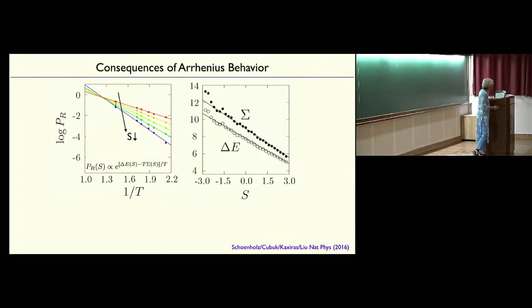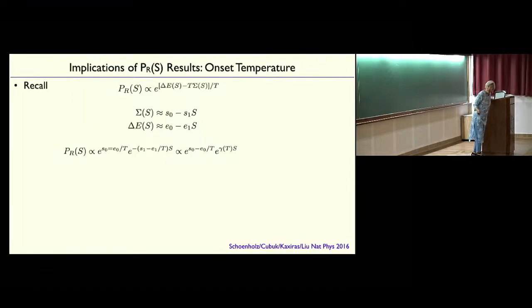All right, so the consequences of this. You see here that the energy barrier is roughly linear and the entropy barrier roughly linear in softness. So it looks something like that. Now let's stick that into this expression. And what do you get? Just stick these dependencies into this expression. You can factor it into two terms. One of them doesn't depend on softness. That's supposed to be a minus sign, sorry, not an equal sign. But this term is purely Arrhenius. It doesn't depend on local structure at all.